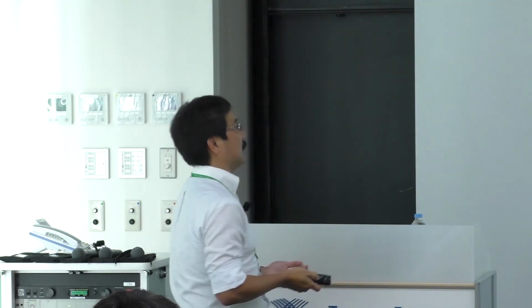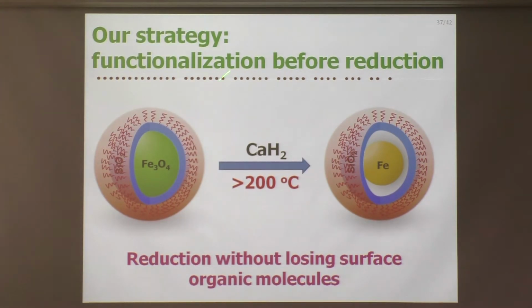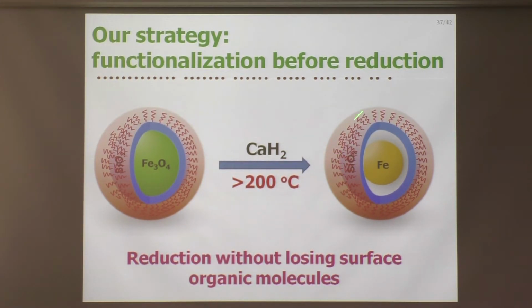So we decided to carry out this kind of modification. Namely, we modified the surface of the sample before the reduction, and then carried out the reduction reaction. Because the temperature is not so high, we expect the surface organic molecules can survive even during the reduction reaction. I'd like to show the result—whether this strategy can work or not.